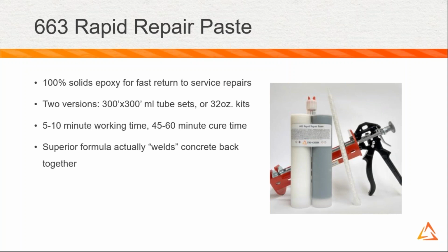If we look at this square picture that we see on here of the material, we've done testing where we've actually taken a 12-inch by 12-inch piece of concrete. We've cracked it down the middle. We welded it back together with the 663. We've let it cure and then tried to crack it, and it actually shatters or fractures on each side of the 663. The 663 turns out to be stronger than the actual concrete itself. So it's actually welding itself back together.